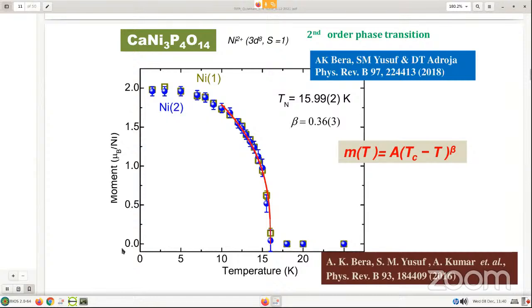So the ordered moment is 0, but when the magnetic phase transition takes place, this site's magnetic moment grows. As I told you, there are two crystallographically inequivalent nickel sites, nickel 1 and nickel 2, and both nickel site moments are plotted here, and the TN, the antiferromagnetic Néel temperature, is found to be 15.992 Kelvin.